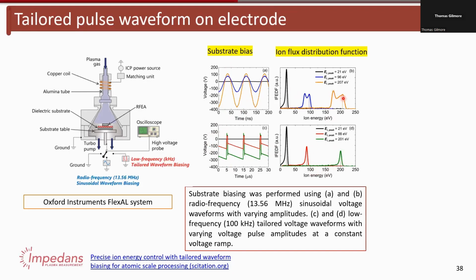Firstly, this gives you more control over the etch rate, because you're now dealing with a much narrower distribution of energy. So you're dealing with one etch rate from that energy, as opposed to multiple etch rates across a broad range of energies. And again, as you increase the power, you can increase the energy. There are also ways to modify the flux by playing with this. In this case, the base frequency was about 100 kilohertz, something like that.